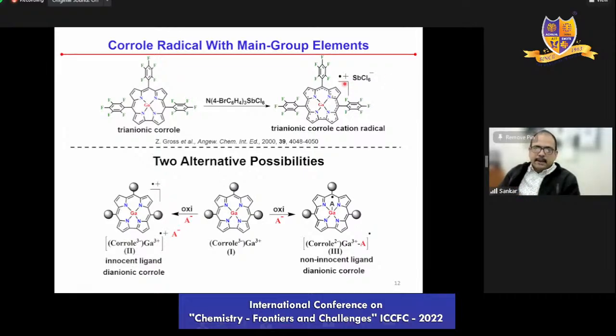Now the question is, was it the metal which got oxidized or the ligand? As I told earlier, gallium is not the metal ion which is going to get oxidized, so it has to be the ligand. So now the ligand has got oxidized, and people have found an EPR signal for a free electron, which is because of the radical. Now what we wanted to see is, is it true that you have a structure with 2 NH and then 1 radical, or is it something different in this case?